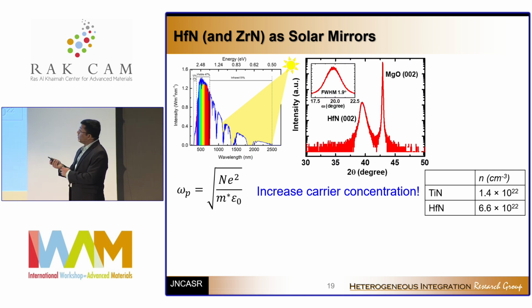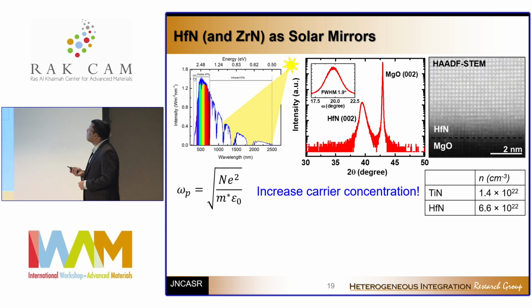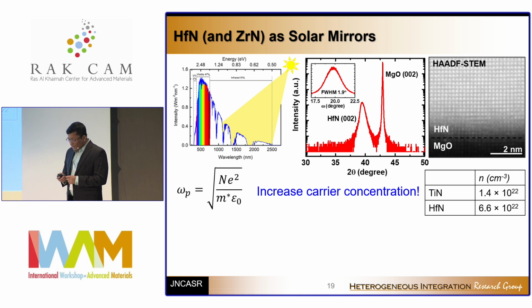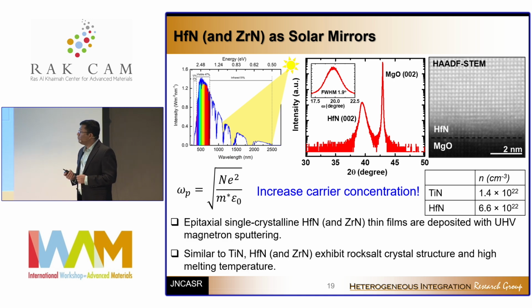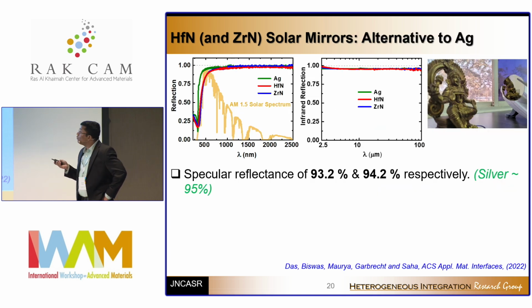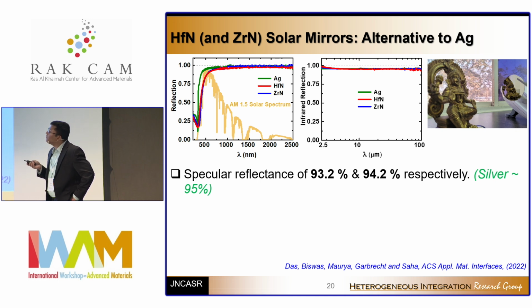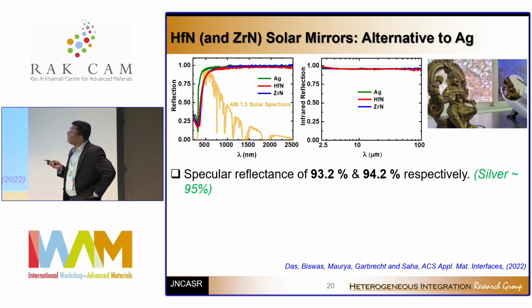So again, we grow them with high quality magnetron sputtering, but ultra high quality magnetron sputtering method. These are perfectly epitaxial, nearly single crystalline films. So structurally, we have tried to make sure as good a crystal quality as we can achieve. And then when you look at its optical properties, if you see this reflection spectra as a function of wavelength, the solar spectrum is presented in the background.